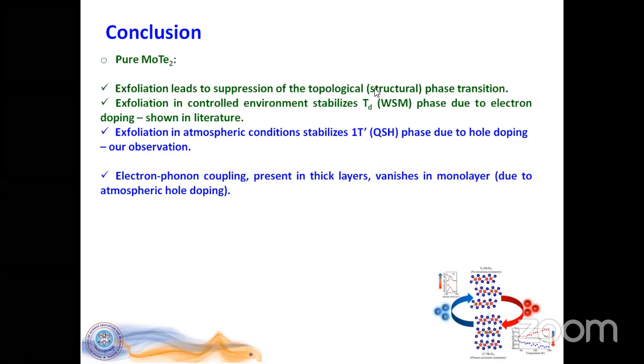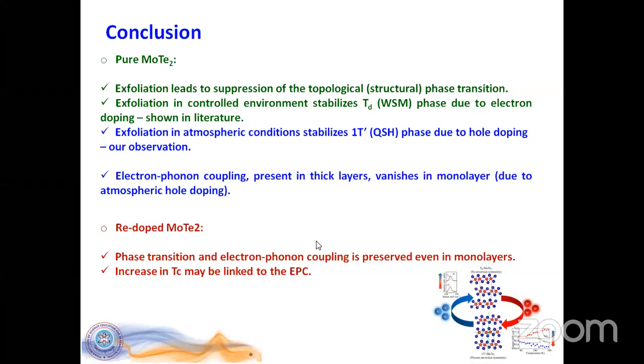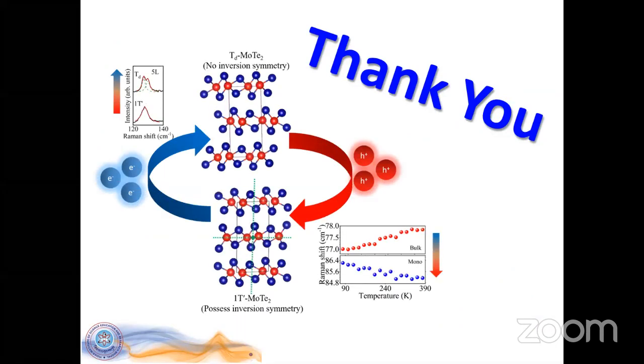And here are the results of our pure system. We showed that the topological phase transition is suppressed when we exfoliate, and then depending on the environment it is exposed to, it can get stuck to the Weyl semimetallic phase or the quantum spin Hall phase. And then electron phonon coupling is there and has a very interesting role. And in the rhenium doped system, we see that the phase transition is preserved even in monolayer. And with that, I would like to thank all of you, and thanks again for listening to me.